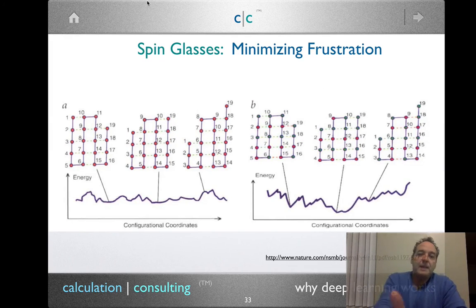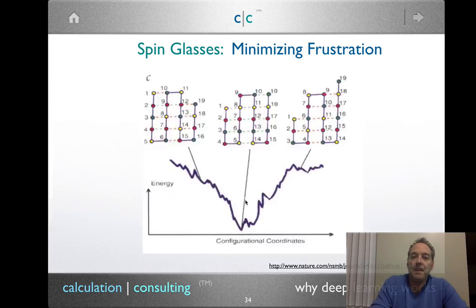So in the upper case, we have an energy landscape of a simple polymer. In that energy landscape, it's fairly flat, and there are lots of local minima, and they're all sort of equivalent to each other. As you start adding structure or layers of connection points where the polymer has to stick to itself, the energy landscape becomes convex. Now, of course, it's not perfectly convex. There are lots of little local saddle points, but it actually becomes convex. And so this concept is called minimizing frustration.